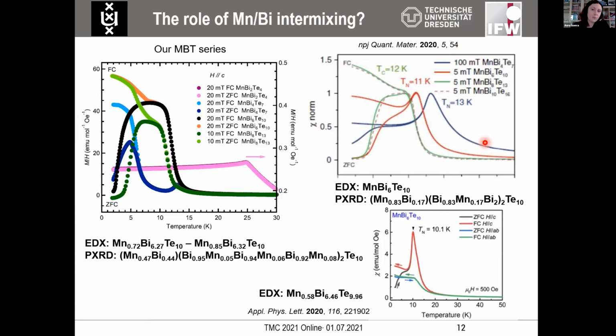So you may have some sub-stoichiometric phases, you may have some voids in the cationic sites, or also the ratio between the manganese and the bismuth in each position, because it may promote a different type of coupling between the central position and the outer position. So far, there is no consistent theory that would describe all the possible cases, just because it is also very variable. But those of you who are used to this notation may notice that I here show the example of 1610 compound,